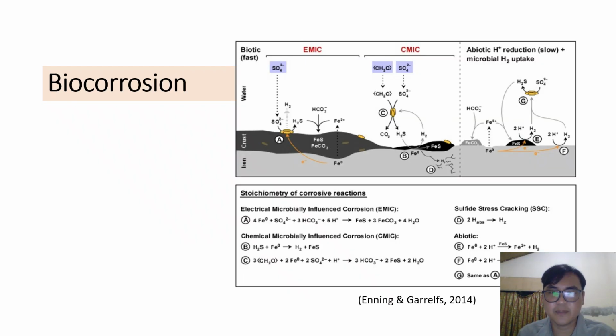This figure contrasts the rapid mechanisms of microbially influenced corrosion on the left against the slower abiotic processes on the right side of the image. On the biotic side, bacteria accelerate corrosion through two pathways, which are EMIC, shown by pathway A, where bacteria attach to the surface and strip electrons directly from the metal, and CMIC, shown by pathways B and C, where bacteria excrete corrosive hydrogen sulfides that chemically attack the iron. Conversely, the abiotic side shows standard chemical corrosion. Without the biological catalyst, the reaction is significantly slower than on the biotic side.